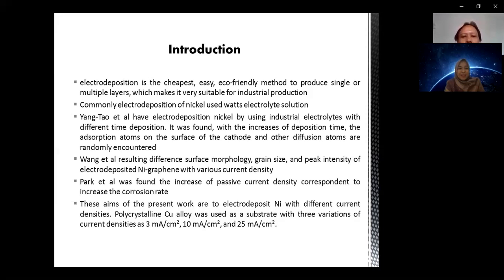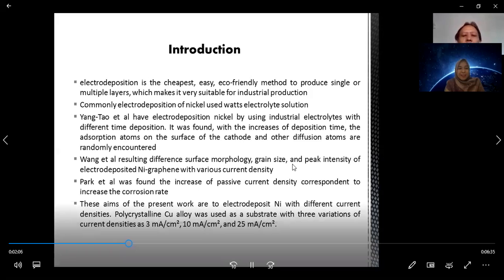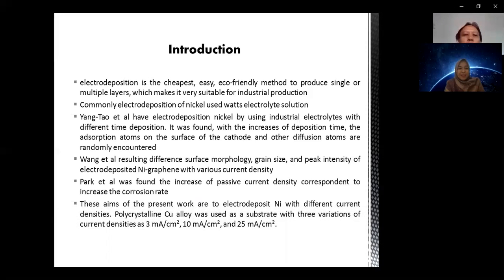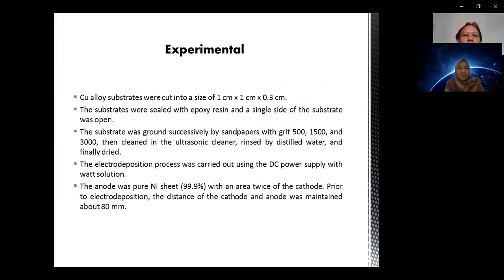The aim of the present work is to electrodeposit nickel with different current densities. Polycrystalline copper alloy was used as a substrate with three variations of current density. In the experiment, we use a copper alloy as the substrate, filled with epoxy resin, and a single side of the substrate is open. The substrate was ground successively by sandpaper with grades 500 until 3000, then cleaned in an ultrasonic cleaner, rinsed by distilled water, and finally dried.